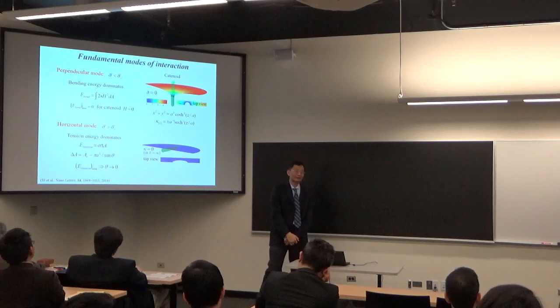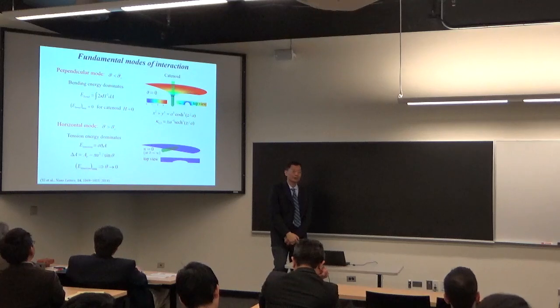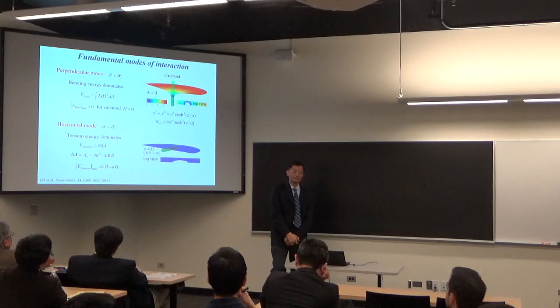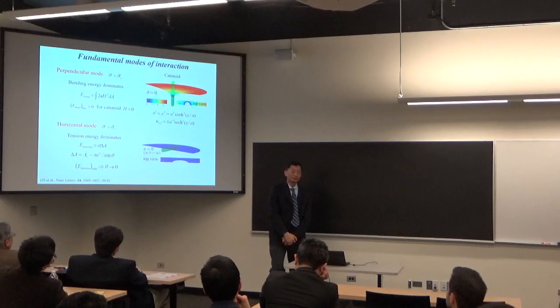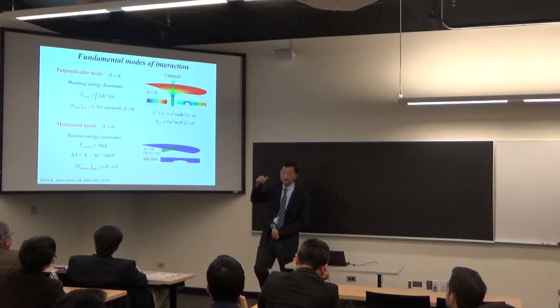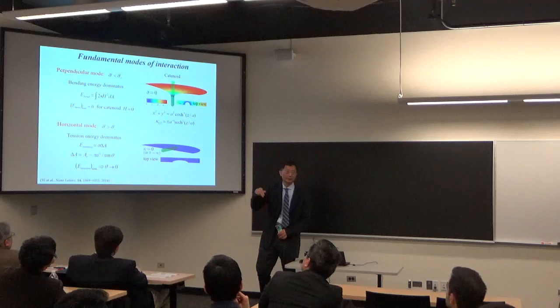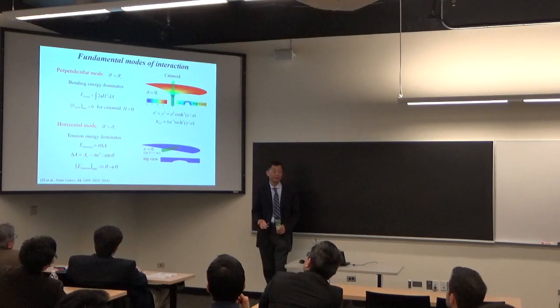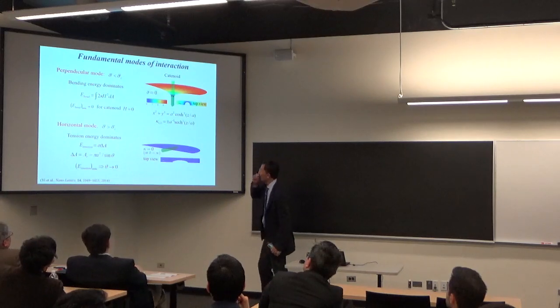This is surprising, right, to an engineer, because in typical plates or shells, any bending would cause energy. But a cell membrane, because it's a fluid membrane, actually has a particular geometric shape, the catenoid. The bending energy is exactly 0. Okay, so this is why, when the bending energy dominates, the nanomaterial wants to go into the cell normal to the cell surface, because the catenoid is a minimum energy configuration, a minimum energy state.